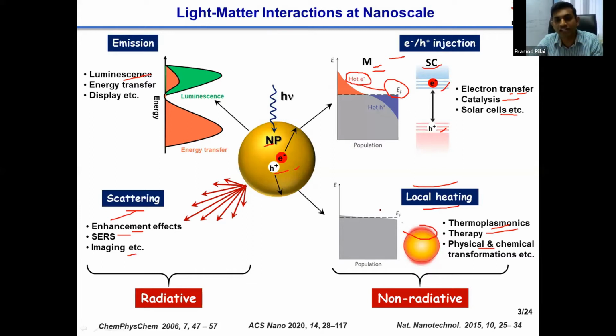Depending on the nature of the nanoparticle and the nature of the surroundings, one of these relaxation processes can dominate. In the area of nanoparticles, our understanding of hot electron chemistry and plasmonic heating is still limited, and active research is going on in these two areas to improve our understanding. One of the major challenges in light harvesting with nanoparticles is to identify the factors which can control these various relaxation pathways, so that one can focus on a particular relaxation pathway to maximize the efficiency of a particular system. This is the biggest challenge in the area of light harvesting with nanoparticles.